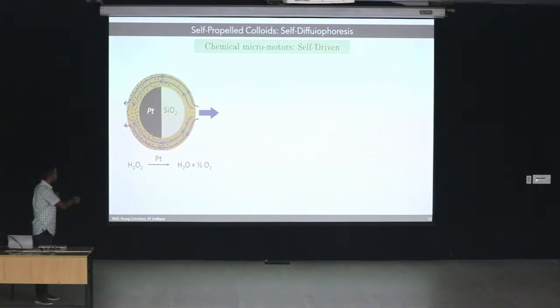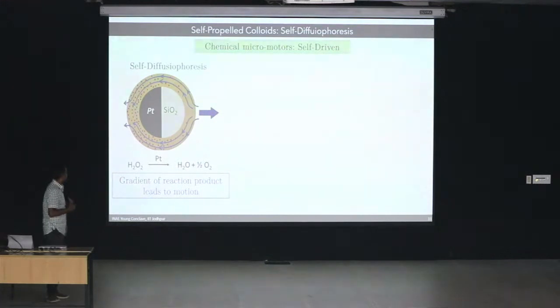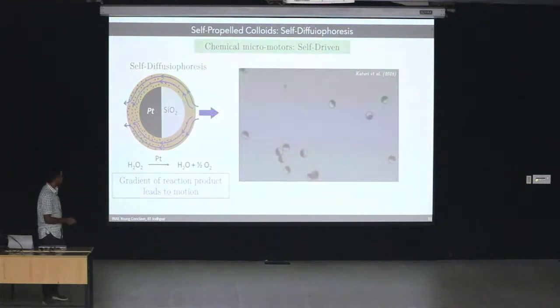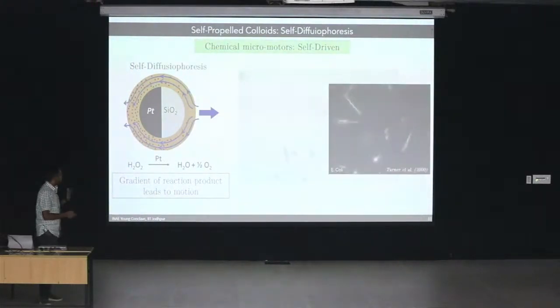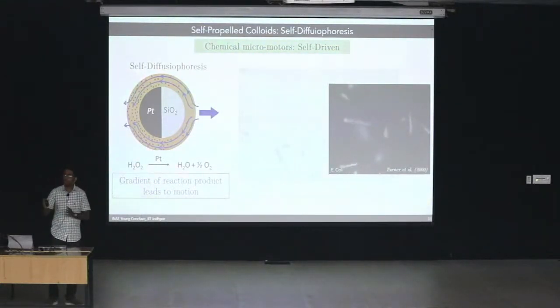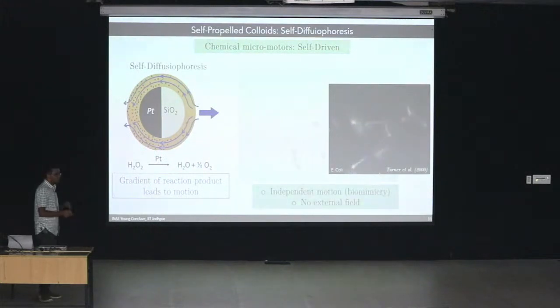That asymmetric distribution of reaction product drives the surrounding fluid flow from silica to platinum because of the osmotic pressure they create. And since these systems are overall force free, we are not applying any external force on them, to balance the linear momentum, these particles drive themselves in the forward direction. So this mechanism is known as self-diffusophoresis because this is created by the gradient of reaction products. And we end up getting these very nicely moving Janus particles. And they represent in a way how bacteria would try to move, all of them performing independent motion in different directions. So we get these active Janus particles. They do not require any external field and they are self-propelled.